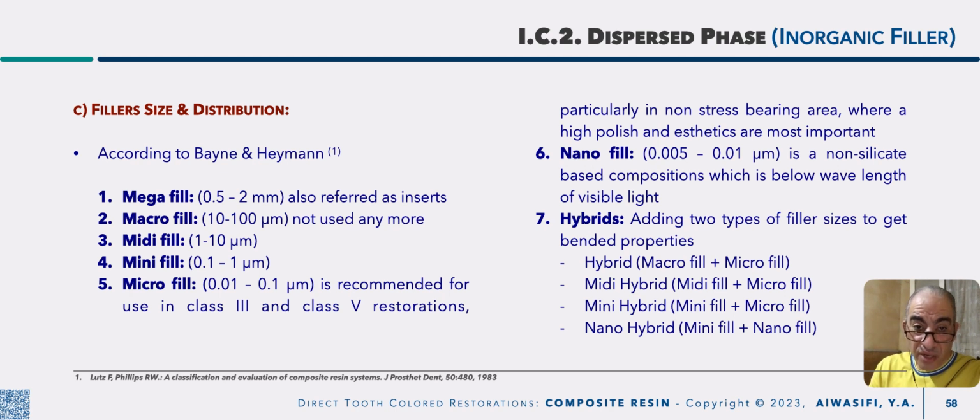Why are large particles aesthetically unacceptable? A large silica particle is translucent like glass, because there is no bond between the resin and the filler. When you finish your restoration, or under occlusal loading force, any abrasive activity at the surface will pull the filler particle out of the mix of the material, leaving a rough surface.